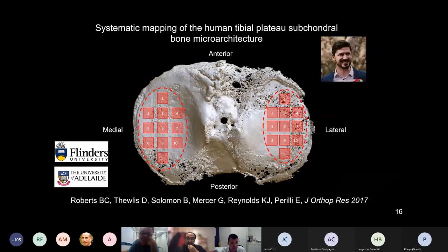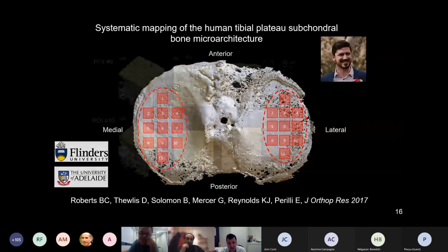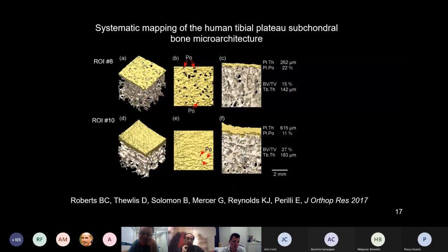And this was the study carried out together with the group at Uni Adelaide, with Dominic Kulis, who was part of this too, and he still is, and Brian Roberts, whom we co-supervised. We scanned, and he developed a protocol for scanning the entire human tibia with microCT, without coring them. So this is virtual coring, where with 17 micrometer resolution, we are able to look at the pores in the cortex of the tibia, so the subchondral cortical bone, the layer just below the cartilage. You see pores, regions. These are regions of 5 millimeter thickness, and in yellow we highlight the cortex, and in white the subchondral trabecular bone underneath.